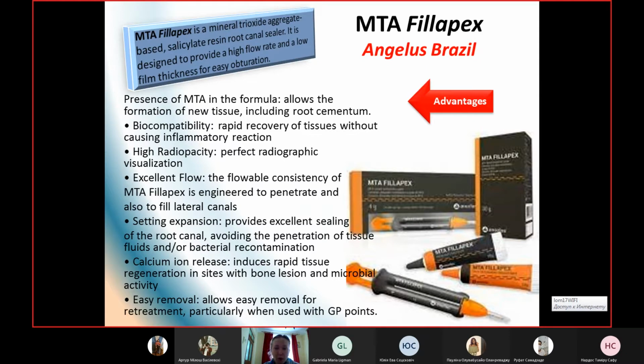Biocompatible, rapid recovery of tissues without causing inflammatory reaction, high radiopacity, perfect radiographic visualization, excellent flow. It is designed to flow into lateral canals even. Setting expansion is another positive quality. It provides excellent sealing of the root canal, avoiding the penetration of tissue fluids and bacterial recontamination. Calcium ion release induces rapid tissue regeneration in sites with bone lesion and microbial activity, and easy removal in the case of retreatment, particularly when this material is used with gutta-percha points. It is available in paste formulation in a syringe. So, MTA Fillapex.